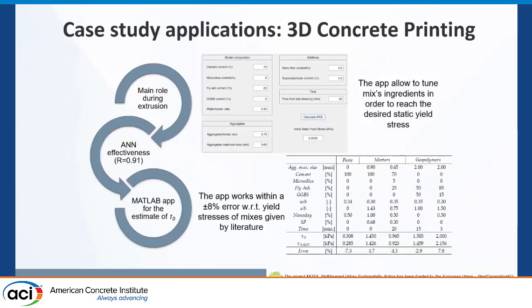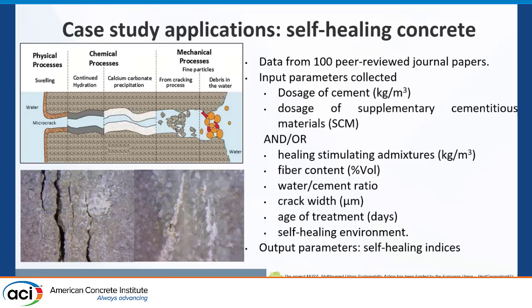Obviously, we wanted to check the reliability. So my student, Francesco, was standing there with the oranges, which he picked up randomly, and said, I want to print some mixes. So we ended up with a paste, we ended up with a mortar, we ended up with a mix containing geopolymers. So we designed these mixes with the aid of the neural network. We had information from the neural network on the rheological properties, the yield stress, which was this. The neural network predicted these values on the second line. We cast the mix, we printed it, we measured the property with a rheometer, and we ended up with predictions which had an error maximum of about 7%, which is, by the way, acceptable, considering also the large variability of the information that you have.